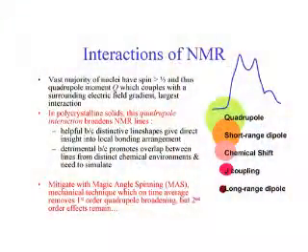But to make some sense of our free induction decay, the time series that we acquire, we transform this and we look in the Fourier domain for shifts away from the Larmor frequency, which are actually functions of interactions that give us the structural information. This is sort of a first-year overview of these interactions, the sort of relative magnitudes. That rather avant-garde diagram on the right-hand side shows that the quadrupole line shape is very broad and indistinct.